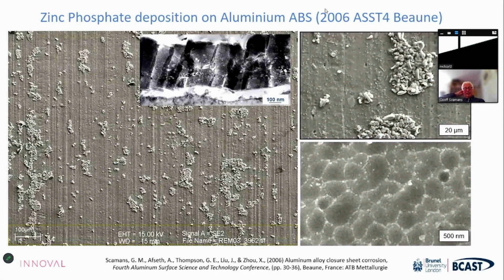This also enabled us to see that although the automotive companies still persist in putting zinc phosphate down on aluminium automotive surfaces, there's actually no need for it. It doesn't really go down very well, although most German automotive OEMs still like to have zinc phosphate on their surfaces for some really obscure, bizarre reason. But you can see if you do some careful ultramicrotomy, again, this is probably Chiron doing this, that the zinc phosphate crystals actually float above the surface of the aluminium sheet, and the actual adhesion is provided by the fluorozirconic or fluorotitanic acid pretreatment that's put on after the phosphating process. So this is where we discovered that it was the rinse after phosphating that was controlling the properties, not the zinc phosphate itself.